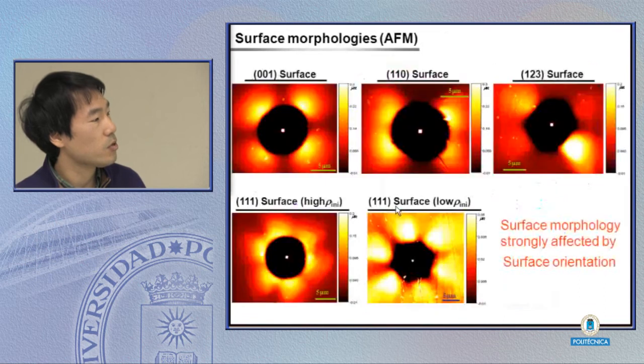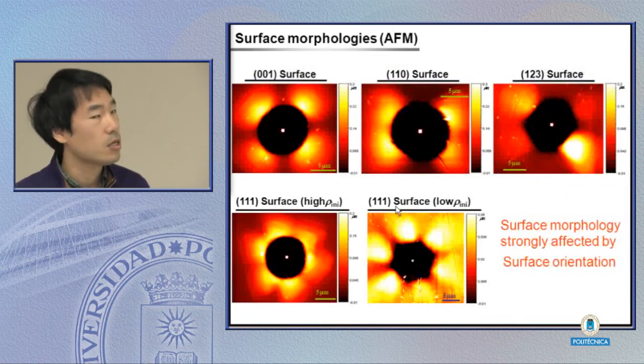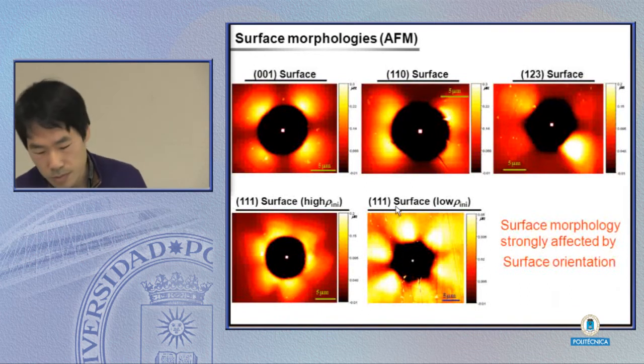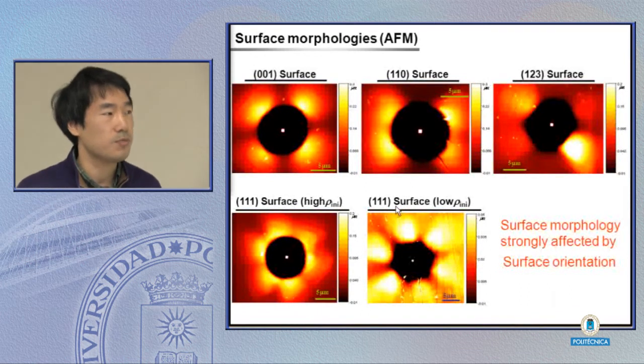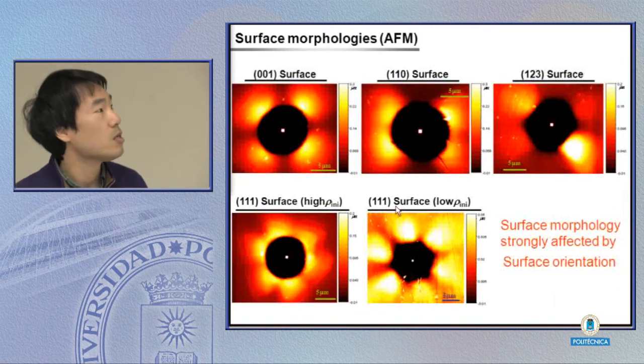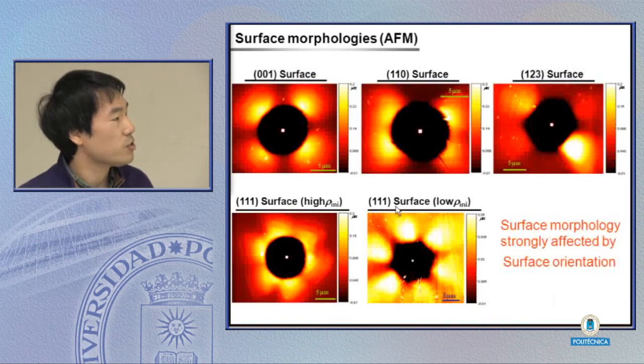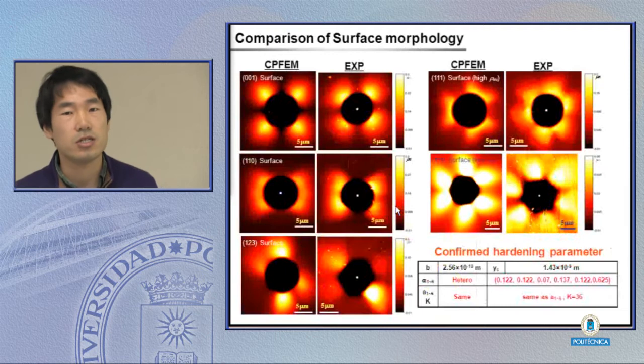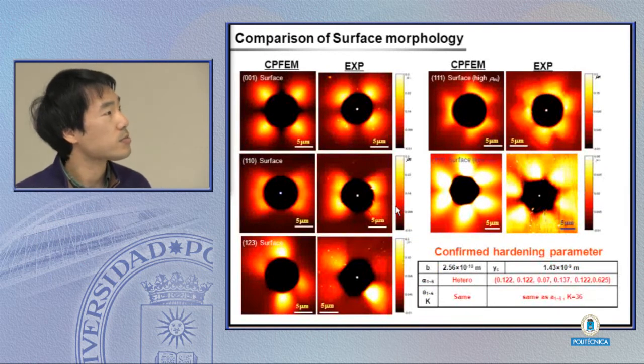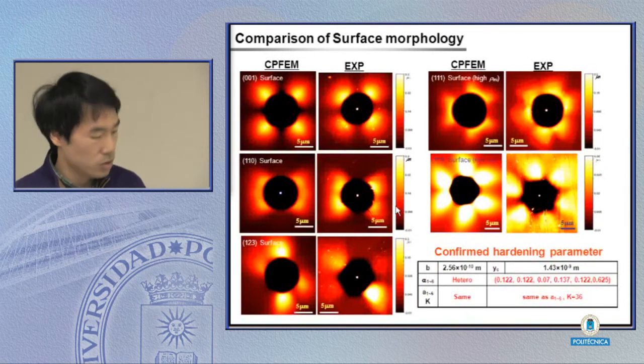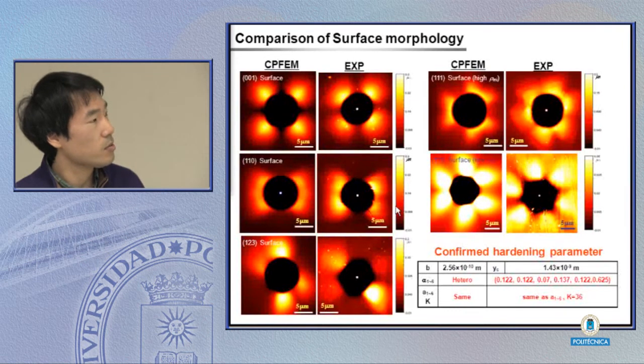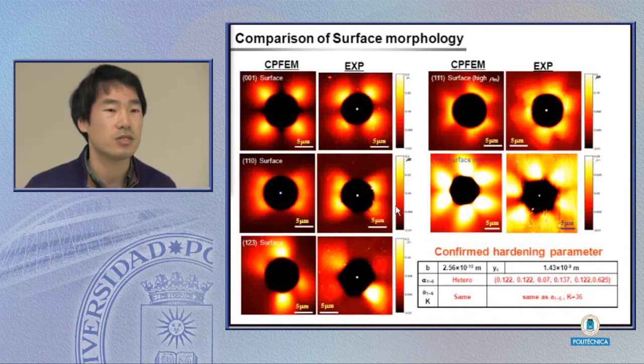And we see the orientation effect like this. This experimental result can be reproduced by the FEM calculation by only using the different initial dislocation density. So we do exactly the same simulation, same data as the experiment.